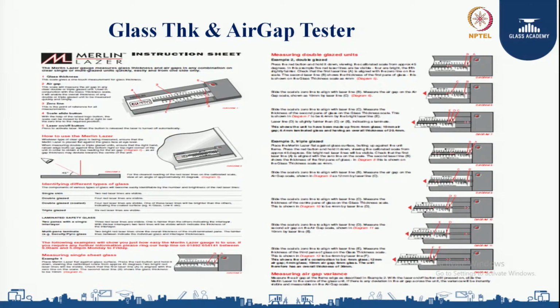Once I press the button, I get a minimum of 4 lights indicating surface 1, surface 2, surface 3, and surface 4. Measuring from right to left, the first line to the second line indicates the glass thickness, the second line to the third line indicates the air gap between the DGU, and the third line to the fourth line indicates the second glass thickness. This air gap tester lets you check glass thickness as well as air gap inside the DGU, and can also measure coating surfaces or trace any PVB layer present.